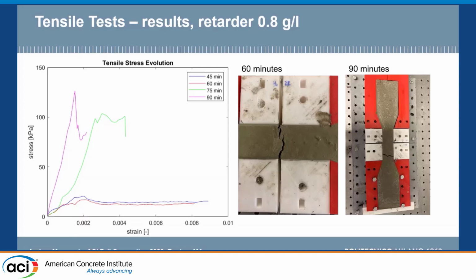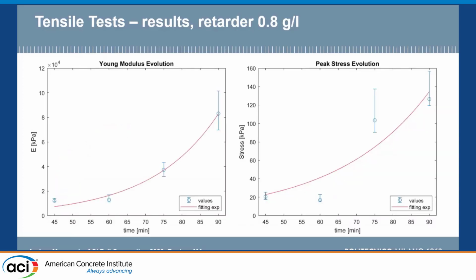But differently from the shear test, we can see that the increase of the strength is a little bit delayed, because at 60 minutes there is no increase of the strength as was happening for the shear strength. In fact, the two curves are very close. But we can still see an exponential increase of the strength if we consider the 75 and 90 minutes.